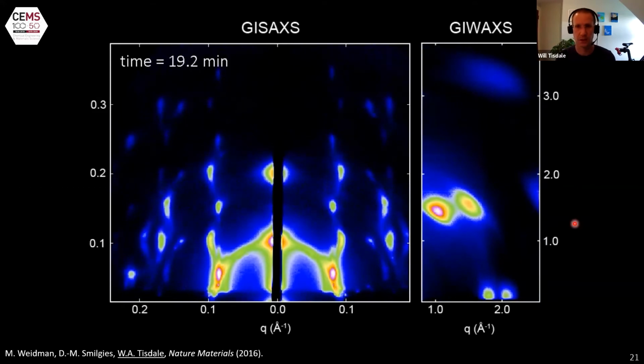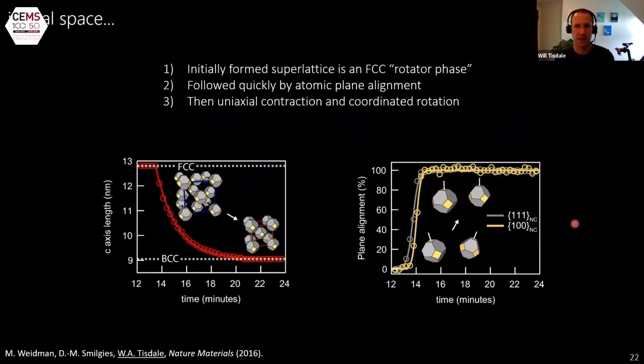So Mark did the painstaking work of indexing every frame of this in situ X-ray scattering experiment. And the overall story looks like this. The initially formed superlattice is a so-called FCC rotator phase. It's an FCC structure where there's no particular orientation of nanocrystals with respect to each other. The very next thing that happens once they reach that FCC configuration is that they lock in their relative atomic orientation.